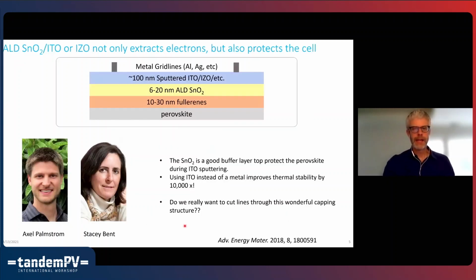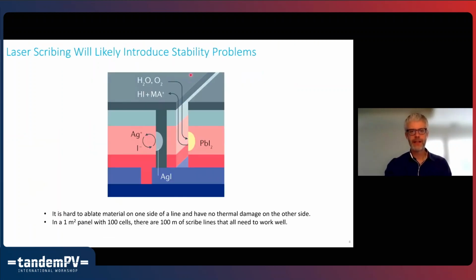And as a reminder, I think a lot of the success that we've had with efficiency and stability was enabled by the work of Axel Palmstrom and Stacy Bent, who developed ways to use atomic layer deposition to put some tin oxide down, which then served as a buffer layer that allowed us to sputter a TCO. And these materials are less reactive with perovskites than metals, even if halogens work their way up to them, and they're impermeable. And we really like this impermeable layer up there, and it's quite a shame to make it and then take a laser and start cutting lines through it.